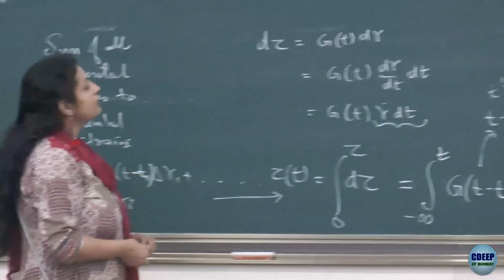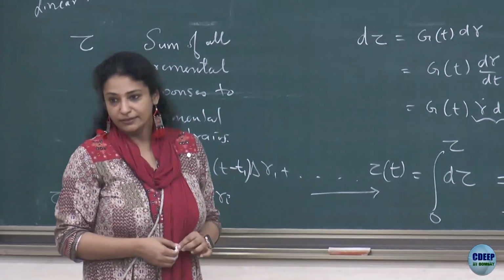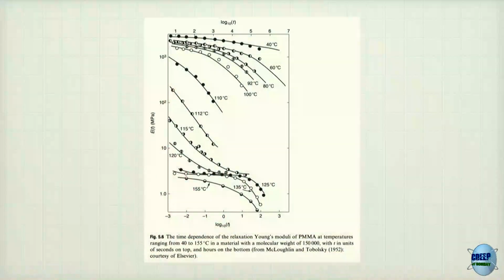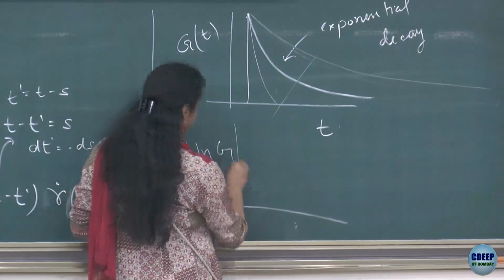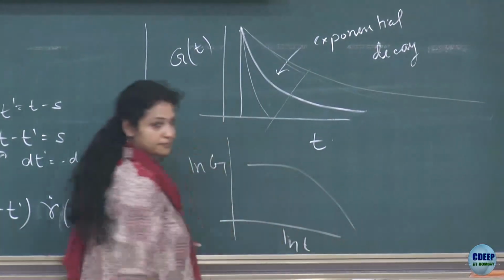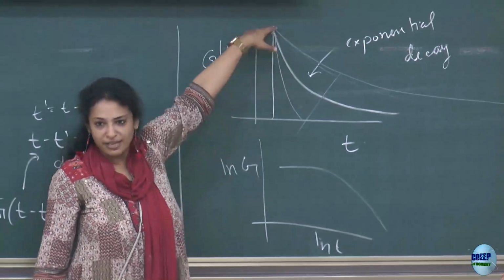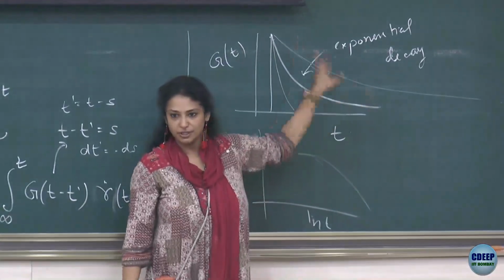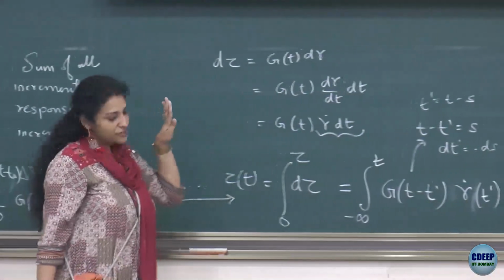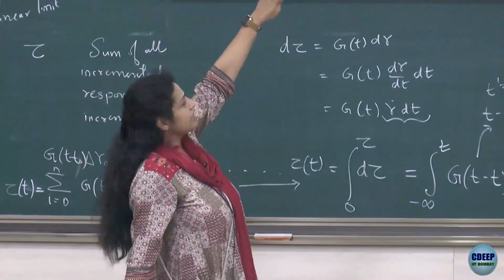So let's take one set of experimental data and see how such measurements show up. This is the Young's modulus, again proportional to the shear modulus that we are plotting. E is 3 times G as we had derived. So this modulus is plotted versus time. Now this is on a log-log scale. If this exponential decay were to be plotted on a log-log scale, it would have looked like this, where this plateau is this very, very short time and this decay is the exponential decay part. And you see that not all the graphs are following this exact trend, but there are traces of this.